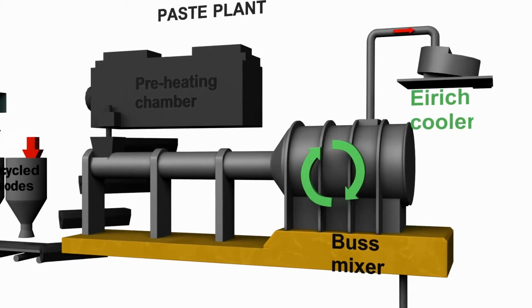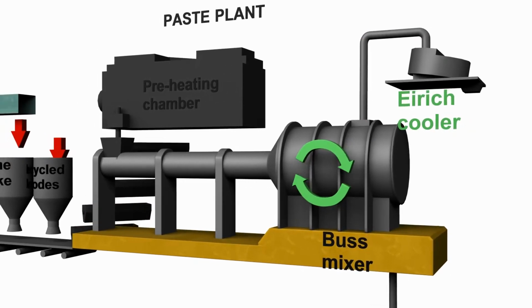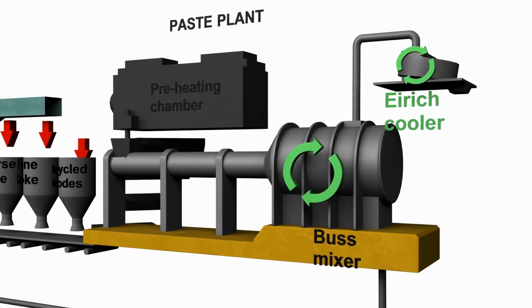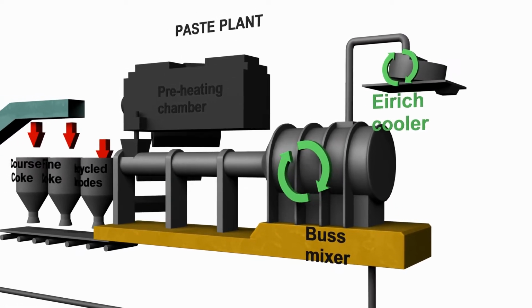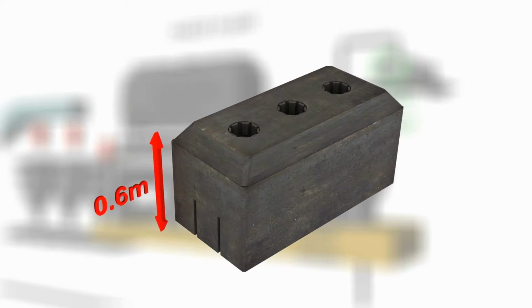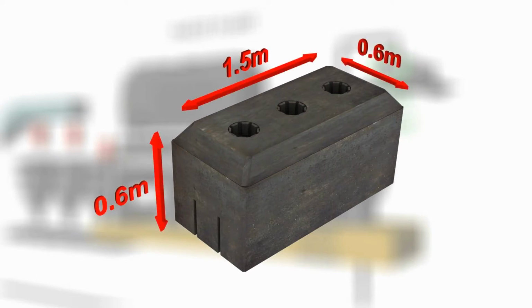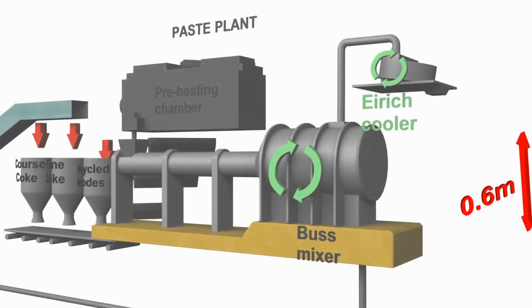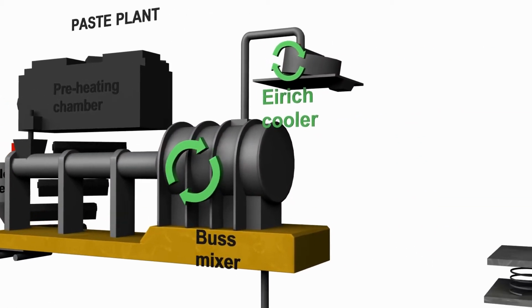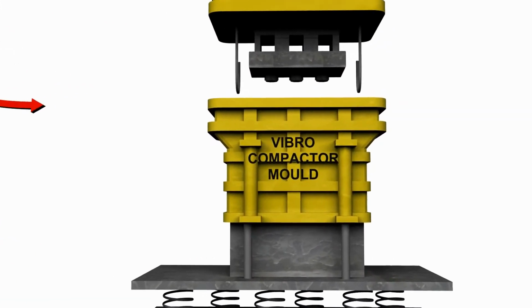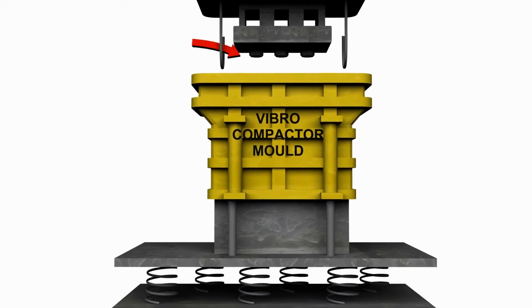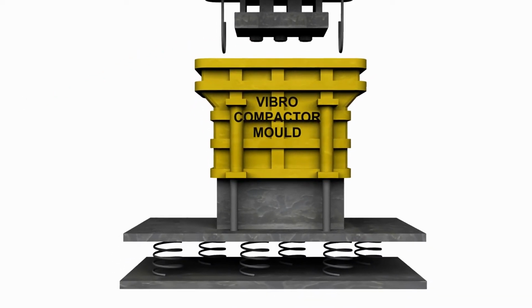The paste now enters a second mixer, the Eirich cooler, where the temperature is lowered as the mixing process continues. The paste is now ready for molding into anodes in the form of large blocks, approximately 1.5 meters by 0.6 meters by 0.6 meters. The process takes place in the Vibro compactor mold.